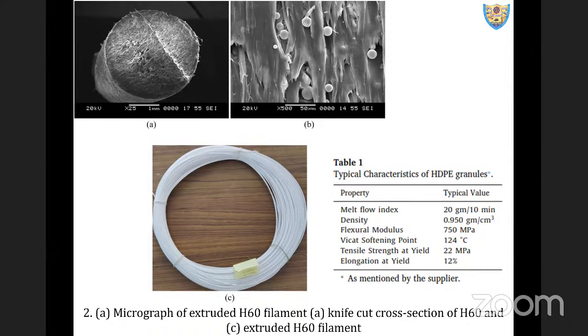And what we found in our studies is that with an increase in GMB content, void percent increases, as I said, because the extruder we used was non-vented type. It is in the range of around 5 to 6% for all the extruded filaments H20 to H60. Now what happens is, as I mentioned in one of the micrographs, these additional porosities or air entrapments, if transferred to printed samples, form a three-phase syntactic foam, which might enhance damping capabilities. And this is what Figure 2A represents, a circular cross-section of extruded H60 filament. Figure 2B is here.